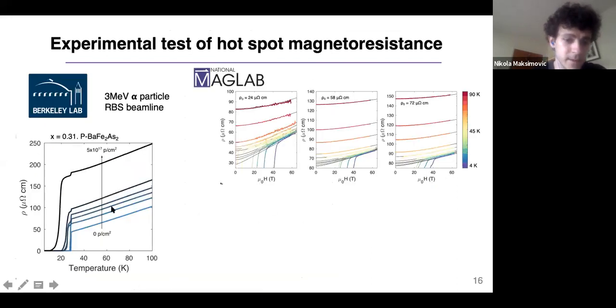So what we did is took samples of optimally doped, the quantum critical Barium-122, and irradiated them with alpha particles at Lawrence Berkeley lab, okay? And you can see the effect on the zero field resistivity. The effect is to basically increase the resistivity in roughly a temperature independent way. Okay, and then several of these samples were taken to pulsed field and were able to do a detailed disorder and temperature dependent experiment on the quantum critical Barium-122.